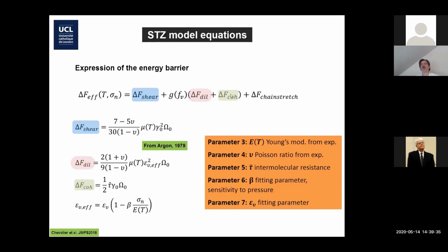You also have the cohesive term with respect to the intermolecular resistance that you have to overcome to make this transformation. There is an effect of the free volume present in the material, taking into account the dilatation strain during a transformation. There is a dilatation strain, and it is known that there is production of free volume. And we added a term related to the fact that when the chain aligns, we need an additional resistance energy contribution to the energy barrier, which is typical to polymers.